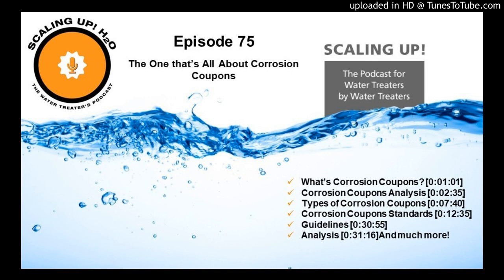Now, if you put a copper coupon in front of a mild steel coupon, what will happen is it will look like you have two copper coupons when you take them out of that duration. So in order to prevent that, you want to put the most noble metal last. Because, again, it's through the line of flow, which flips the whole thing upside down. I don't know if I kept everybody up with that, but that's how I remember it, and that's why they're organized. Another question I get quite a bit is how long should I keep corrosion coupons in the system?